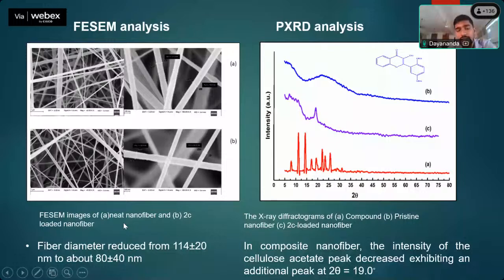This is reflected in the powder XRD. The profile shown in red color is the PXRD of the synthesized compound, which was highly crystalline in nature. But upon incorporating into the nanofiber mat, the crystalline nature was reduced, though it was found to be more crystalline or semi-crystalline than the neat cellulose acetate nanofiber mat. One could also see a shifting of the characteristic peak of the cellulose acetate, shifted towards a lower 2 theta value.